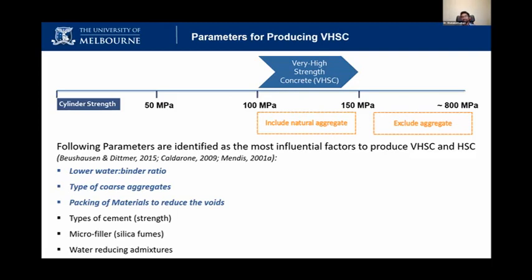For example, sand is very consistent. When we get a sand sample, it's made of quartz, so the mechanical property is very consistent and uniform. But if you source aggregate from a quarry, it may not have the same consistency. One aggregate may have a different property, another aggregate has a different one. That's really a challenge when you are going to make very high strength concrete, because these defective aggregates can initiate the failure of the entire concrete, consequently reducing the strength of the concrete.